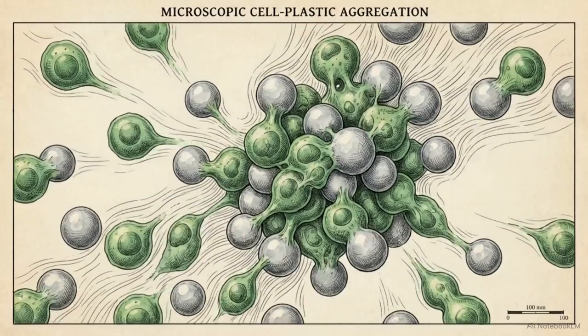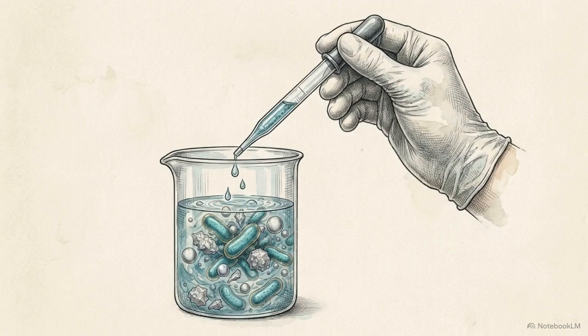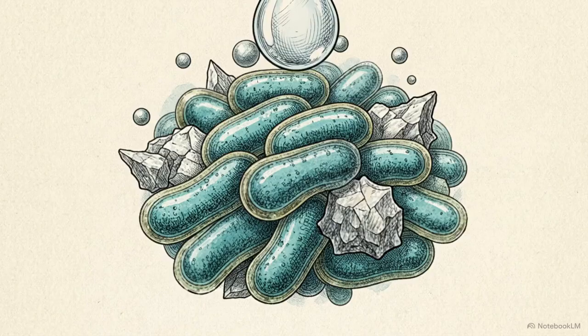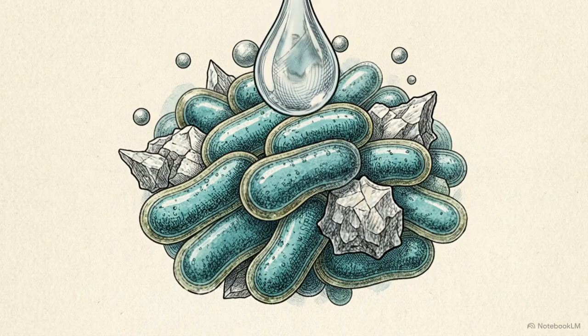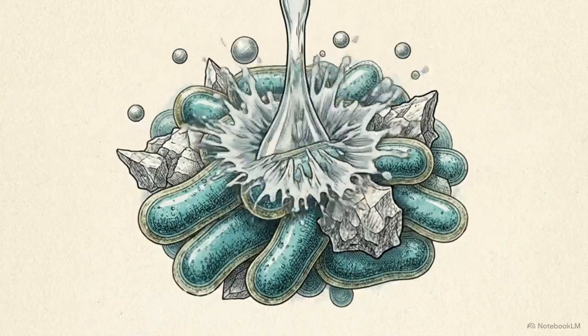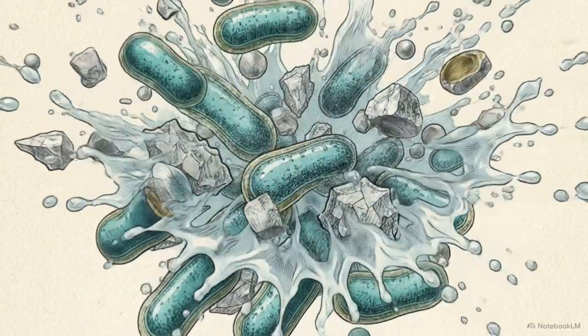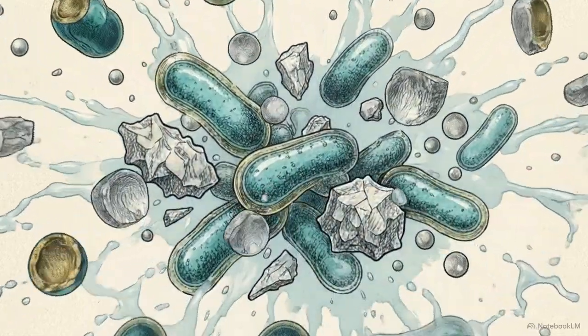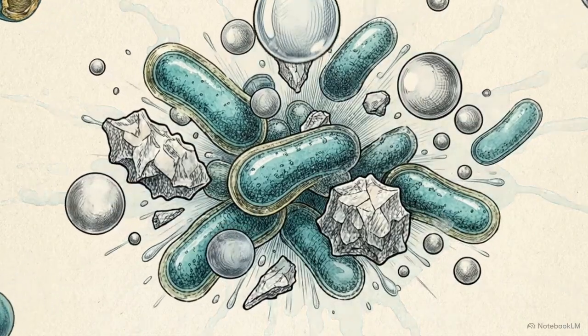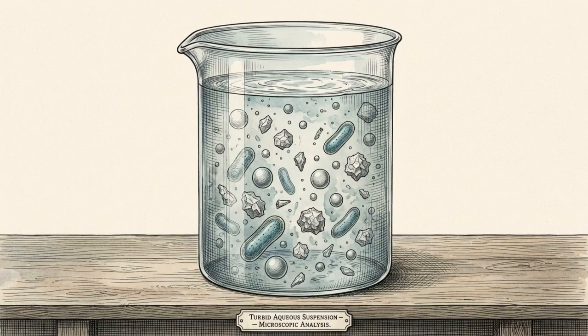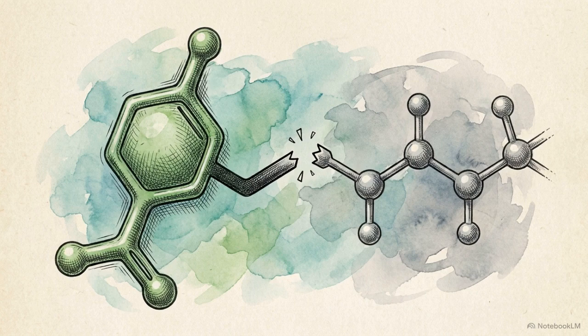pathways cannot replicate. To verify that hydrophobicity is the sole mechanism driving this process, researchers introduced a surfactant called Tween-20 into the clustered suspension. Surfactants operate by lowering surface tension and physically disrupting hydrophobic links between molecules. Immediately upon adding the surfactant, the microplastics and cyanobacteria cells decoupled and resuspended in the fluid, confirming that hydrophobic attraction is the specific physical driver of the capture.